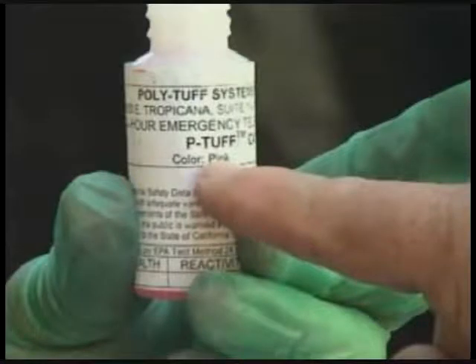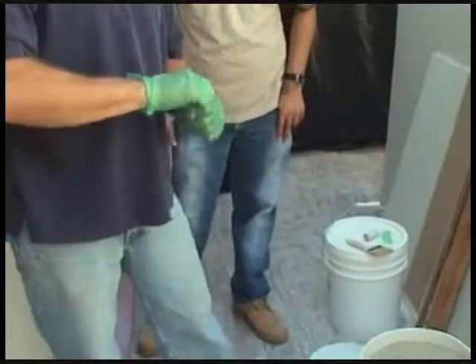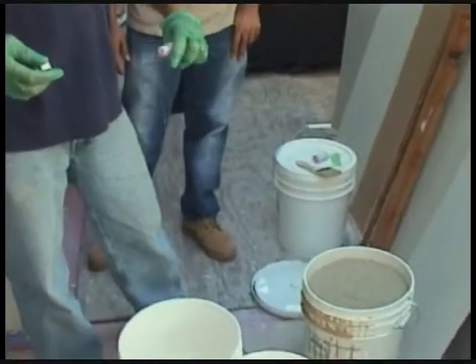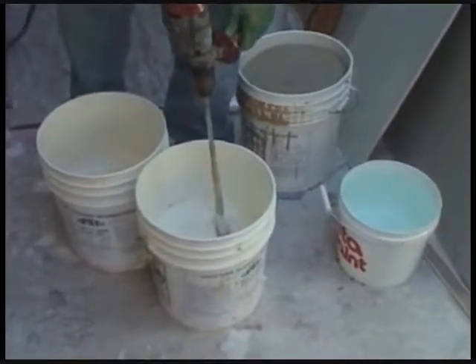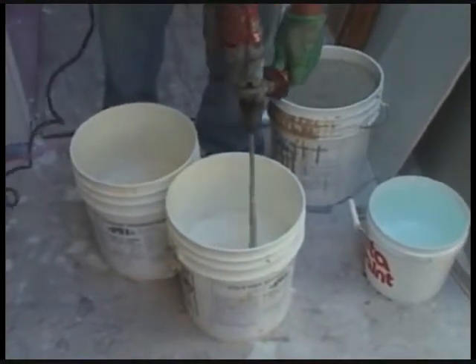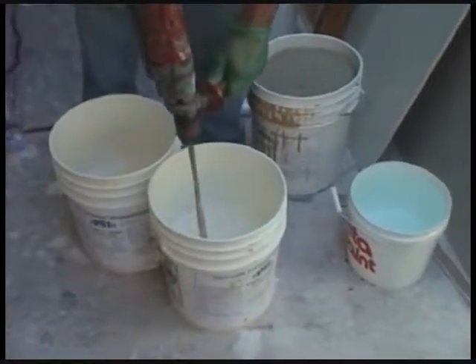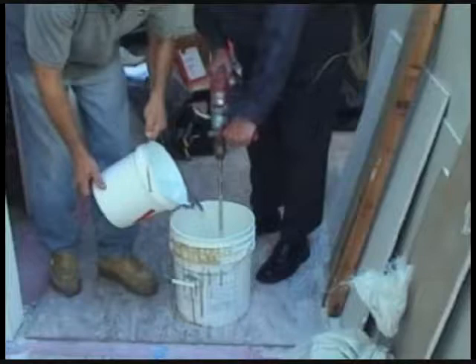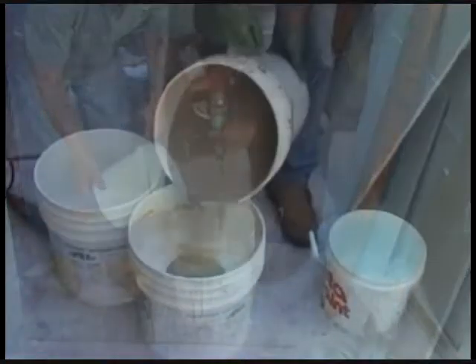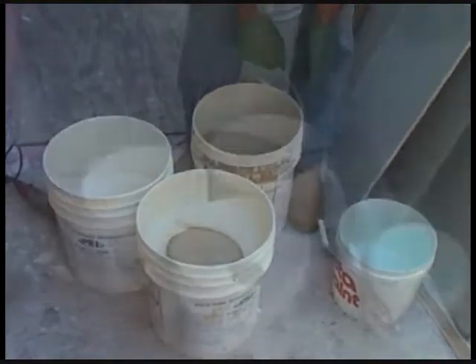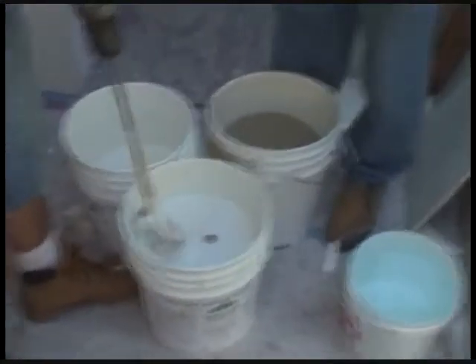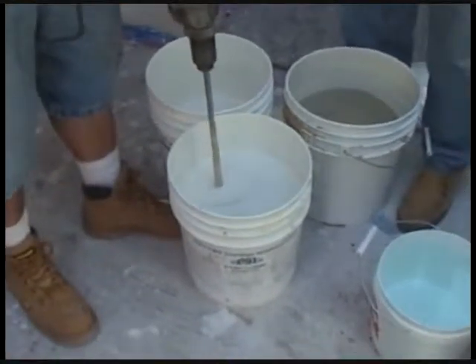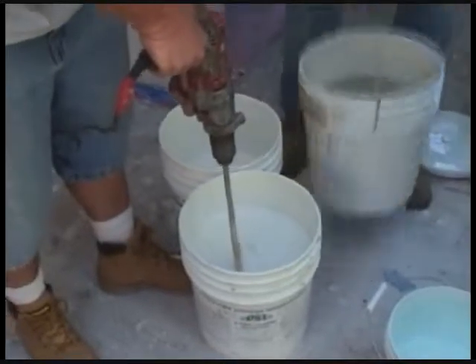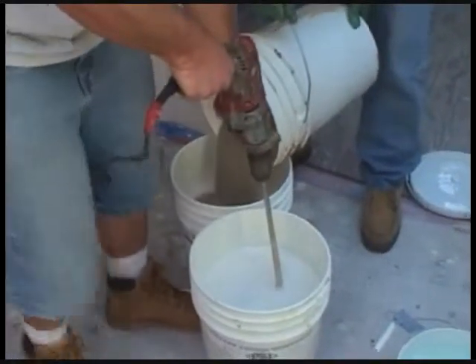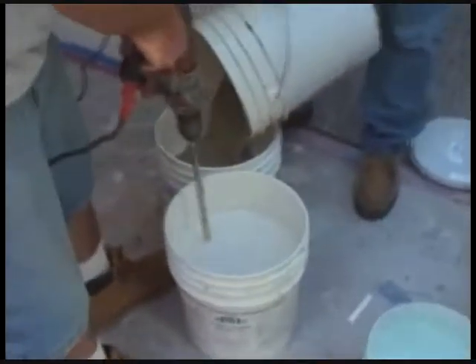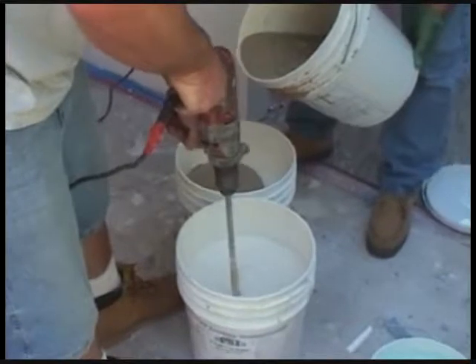One catalyst vial will be divided in two, and half will be used in each of the 2.5-gallon containers of coating. The contractor will mix the catalyst into the coating, then add the water. 2.5 quarts of water will be added to 2.5 gallons of coating. Then the sand will be added. After the water is added and mixed, 2 gallons of sand is poured into each of the 2.5 gallons of coating with the 2.5 quarts of water. The sand is mixed together and creates a sand slurry.